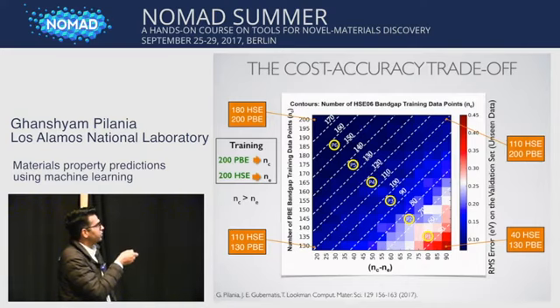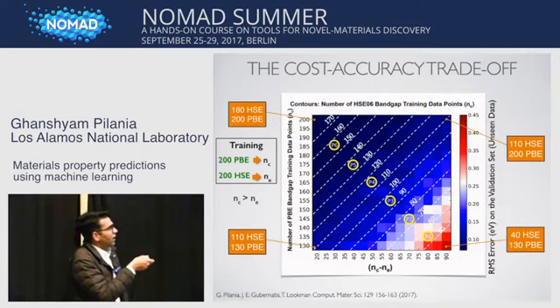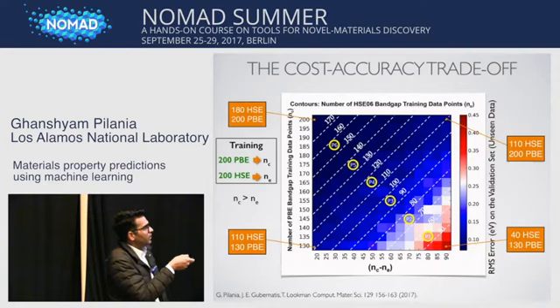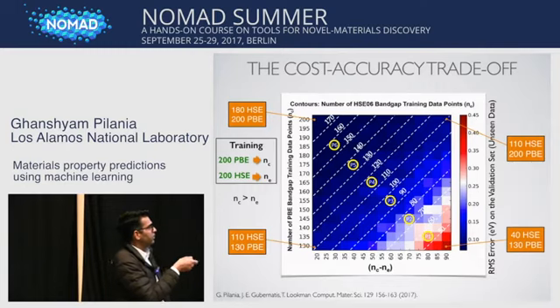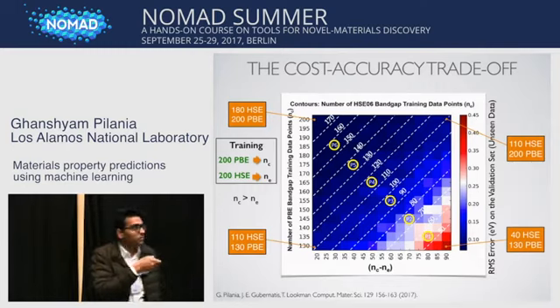So that's the combination we used to train the model, and that was the test set error. And here, because the difference is 90, that means we have much less number of HSE data points, and the prediction performance is actually much worse as compared to this. So if you plot this data this way, then